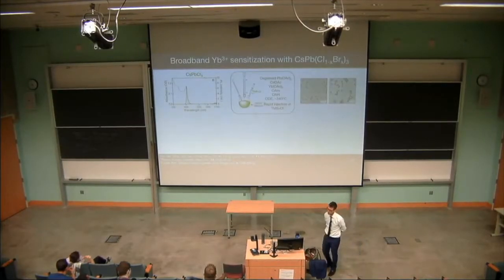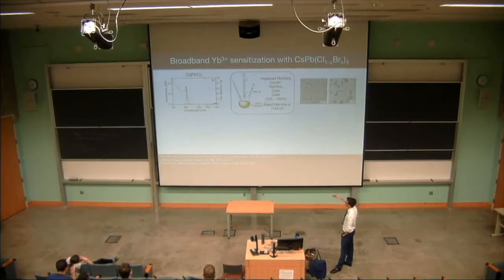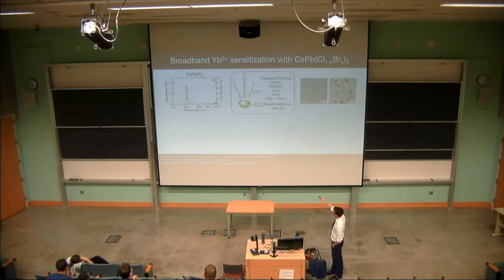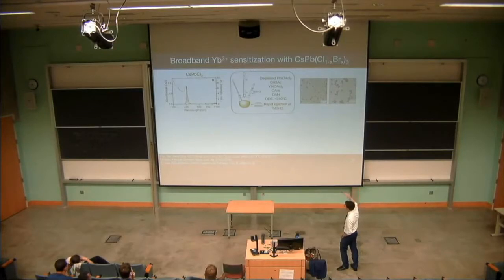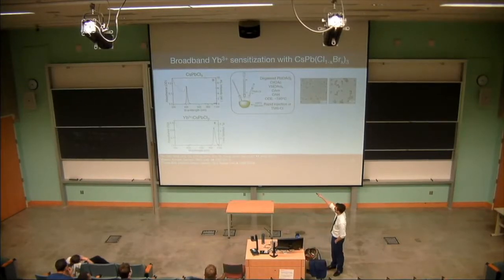That was until about 2 years ago, where a paper from the Song group came out, and then a paper from my postdoc group came out showing that we can introduce these ytterbium dopants into this cesium-lead chloride host lattice. In an undoped sample, this material has a very sharp absorption with an exciton peak, and then this very sharp, very slightly Stokes-shifted luminescence. This original formulation here was made with nanocrystals. However, whenever we introduce the ytterbium, we see a big change. All of a sudden, this exciton luminescence completely died away, and it appears that all of the energy was transferred into this near-infrared region.